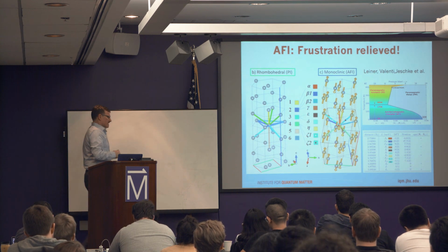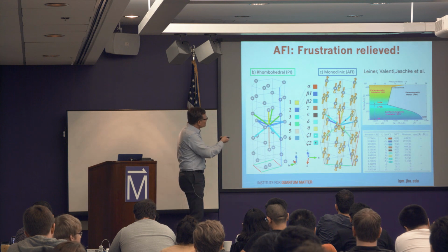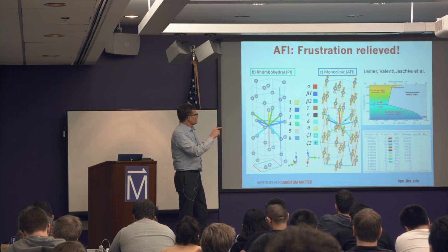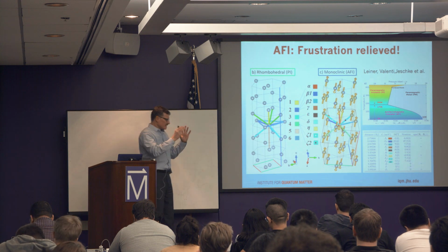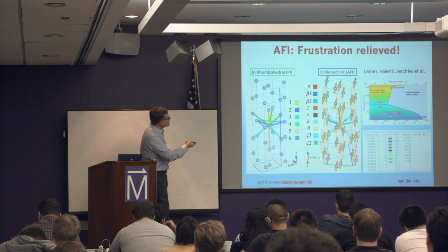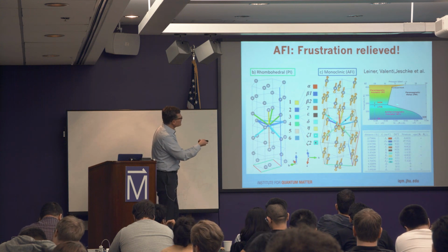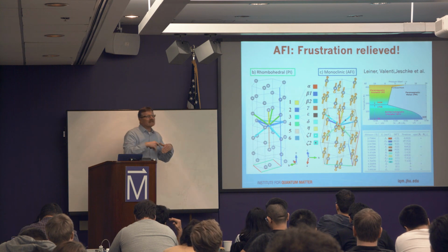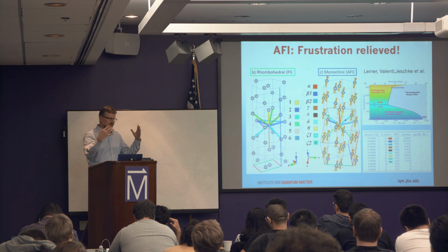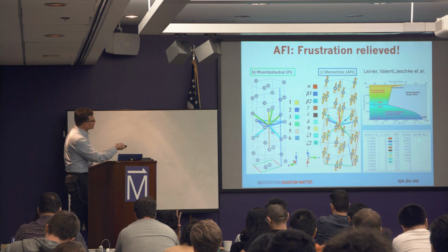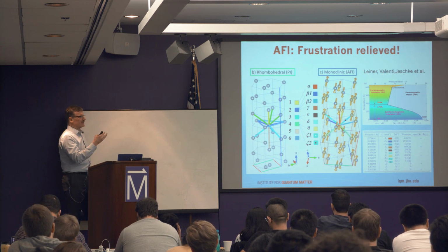But then there's an interesting piece of physics going on at this phase transition where a secondary state is assumed, which has a lower space group symmetry. It goes to a monoclinic structure that presumably costs some, we could call it, lattice energy or structural energy, but correspondingly I'm now able to satisfy every single one of those magnetic interactions.